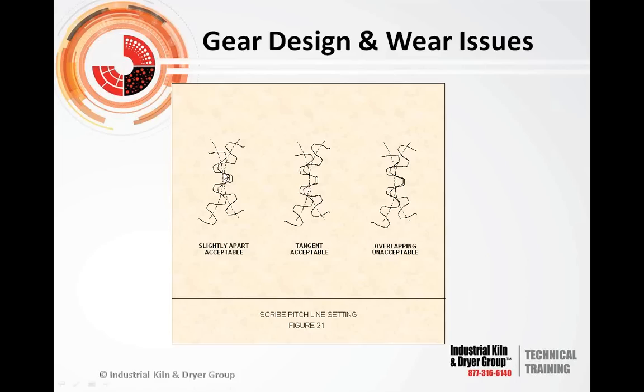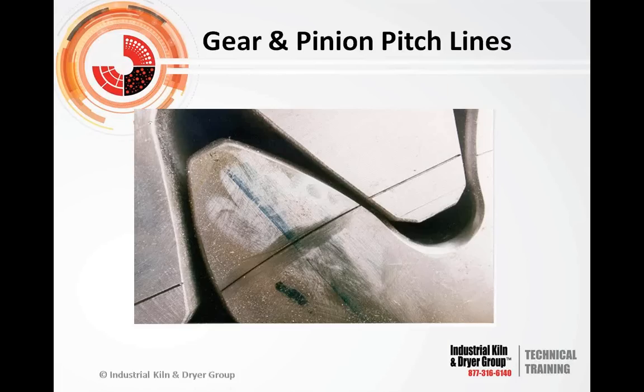So when setting a pitch line on a gear, it's okay on a dryer and a kiln to match the pitch line, because as this gear grows, it's going to separate that pitch line. So if you're slightly separated, it's fine. If you're tangent or even with the pitch lines, you're fine. If you're crossing pitch lines like this, then you're going to have vibration issues. So that's something just to note on a gear and pinion for rotary type equipment like what we're talking about here.